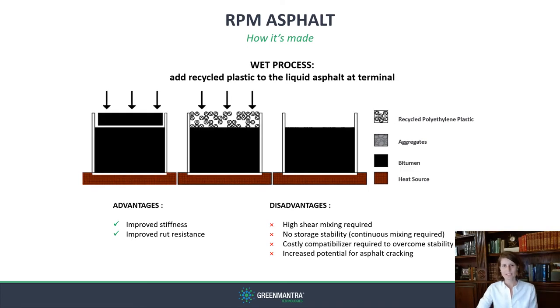The wet process is the technique that Kim introduced earlier as she described the work that was performed by the Plastics Industry Association. In the wet process, recycled plastic particles are added at the beginning of the process to the liquid bitumen. The plastic is fully melted into the bitumen prior to any addition of aggregate. This is a technique that is becoming more preferred for performance-based asphalt, as some preliminary studies have indicated potential performance benefits. The advantages of this process include improved asphalt performance, including better rut resistance.